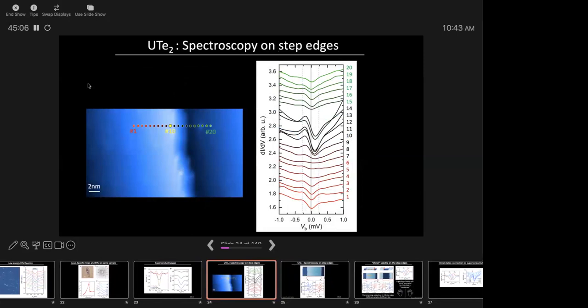Okay. So let me show you some very interesting data that we don't understand on the step edges of the sample. If you look at the step edge, and now I'm beginning to slowly run out of time, I have to hurry. Far from the step edge, number 20 would be this one, number 1 would be this one. So let's start here. This is far from the step edge. You see this wider superconducting gap. And then you get close to the step edge, and you see some very strange feature right at the step edge, which looks like this.